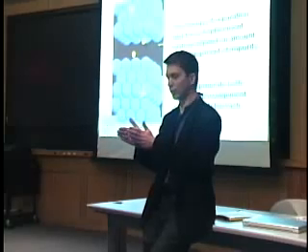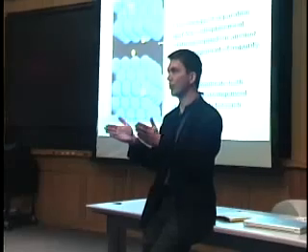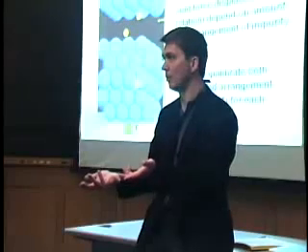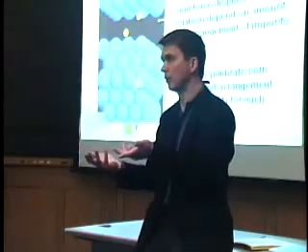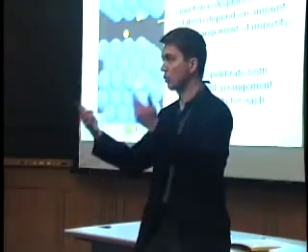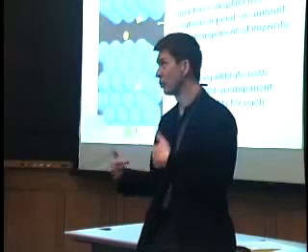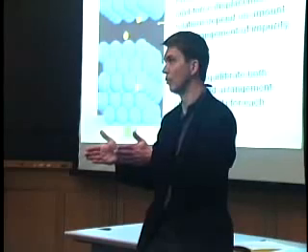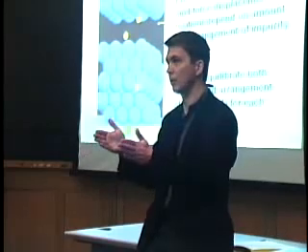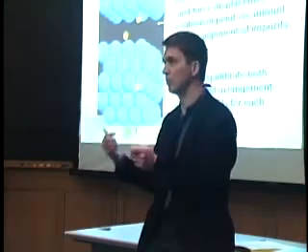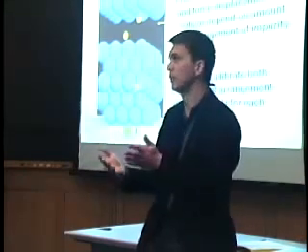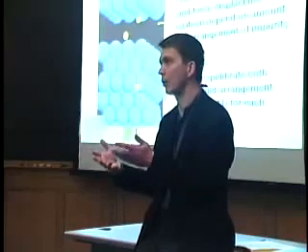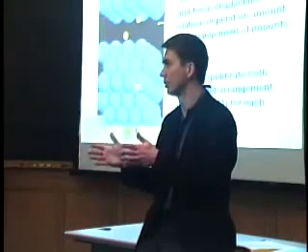Okay? So you pull the crack open a little more. You now have to figure out what happens to that impurity there. Because as that impurity equilibrates, not only its structure, by the way, but also its composition, because segregation to those surfaces is an open system problem. The concentration there is not fixed because it comes from the bulk or from a gas phase. So it's actually a grand canonical problem. It's a constant chemical potential problem rather than a constant composition problem.